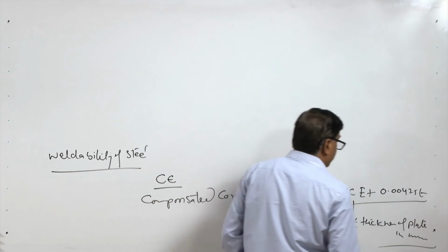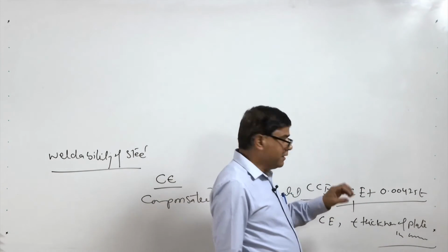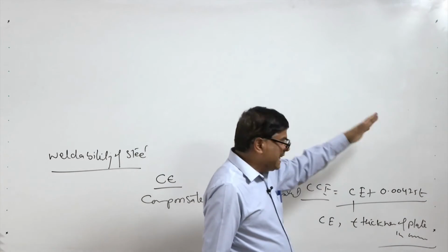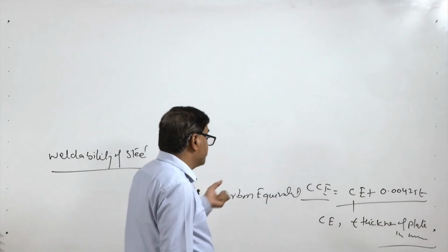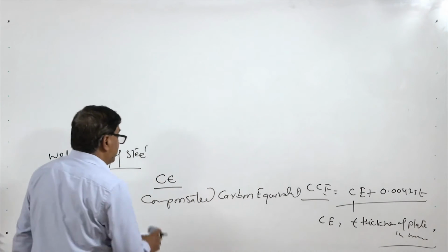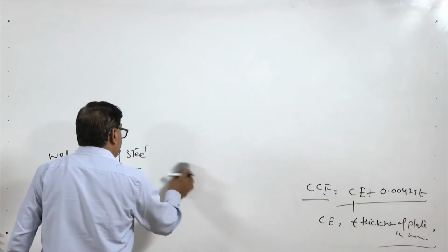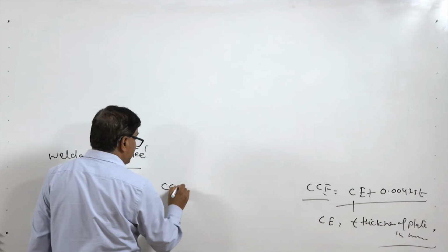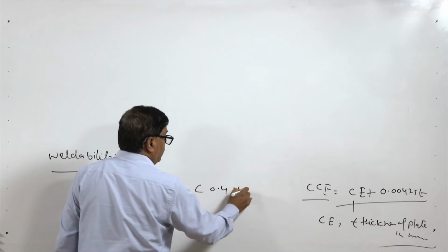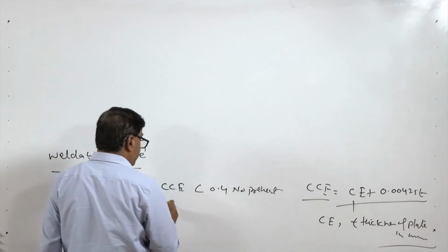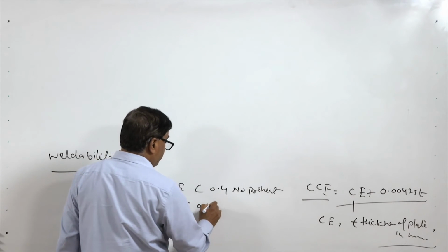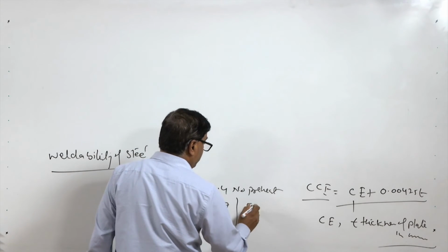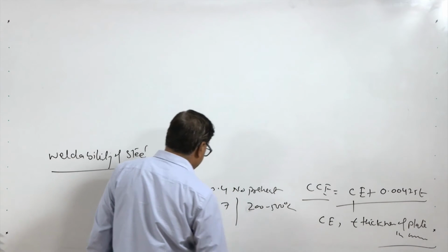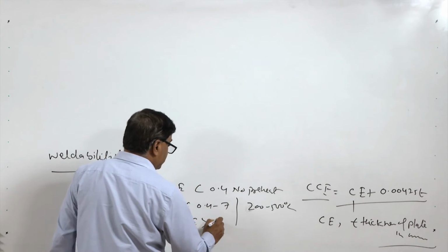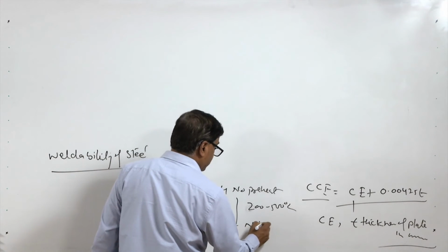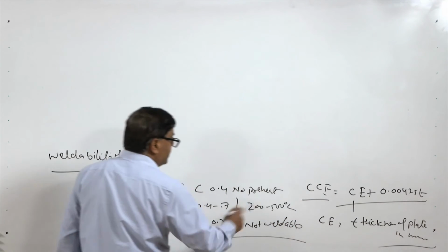So, obviously, even for the steel of a given composition, if the thickness of the plate increases, then it will increase the compensated carbon equivalent, and for the compensated carbon equivalent a different scheme or broad guidelines are used as far as preheat is concerned. So, for CCE less than 0.4, no preheat is used, for CCE in the range of 0.4 to 0.7 a preheat of 200 to 500 degrees centigrade is used, and for CCE greater than 0.7 the steel is not weldable.